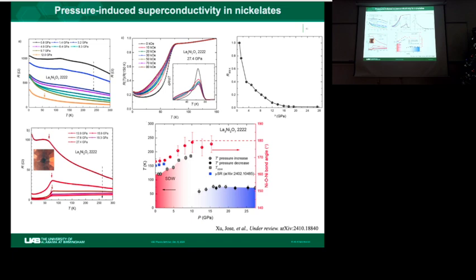So indeed, we saw a sharp drop of resistance right above 15 GPa, as reported in the original Nature paper last year, and the critical temperature matches exactly the reported 80 Kelvin. However, when you apply a magnetic field, this onset temperature doesn't change at all, although there is a broadening at lower temperature and a shift to lower temperature.